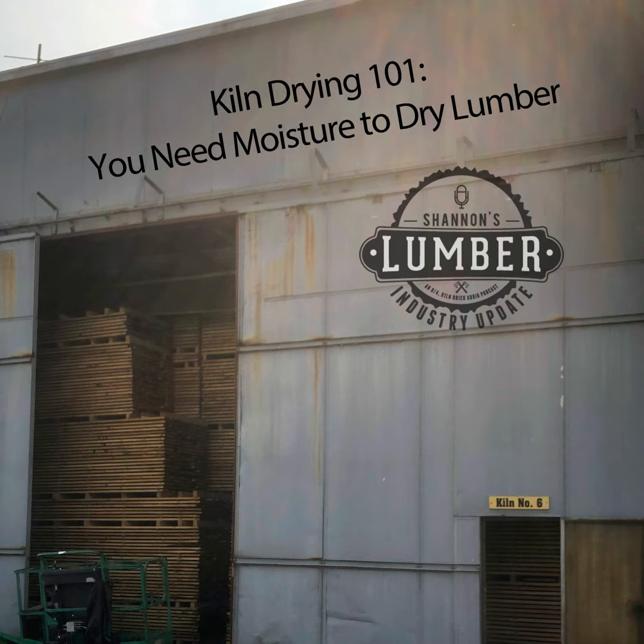Now, certainly you can put it in a kiln without introducing steam, and you can continually check it with a moisture meter. But the problem there is the rate of moisture drop. It will be dropping in moisture, and you may think I'll keep checking it until it gets to 8% and then I'll pull it out. But if it got from 30% to 8% over 48 hours, that is way too fast. Most of these kiln drying schedules take weeks and weeks and weeks, if not months, to slowly, safely, and without introducing tension, get the lumber down to 6 to 8% that is not going to blow apart when you run it over a table saw.